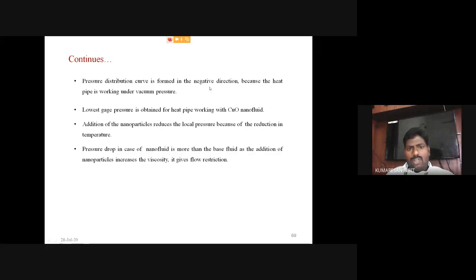Then the pressure distribution curve is formed in the negative direction because the heat pipe is working under vacuum pressure. Then the lowest gauge pressure is obtained for a heat pipe working with copper oxide nanofluids. The addition of nanoparticles reduces the local pressure because of the reduction in the temperature value. Then the pressure drop in the case of nanofluid is more than the base fluid, as the addition of nanoparticles increases the density as well as the viscosity. It gives restriction to the fluid flow.